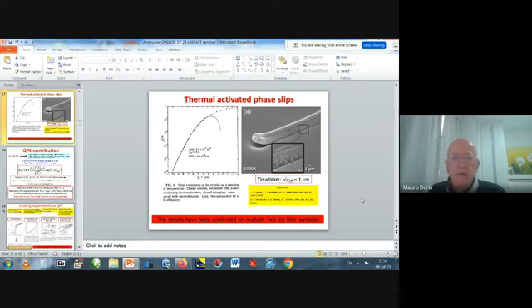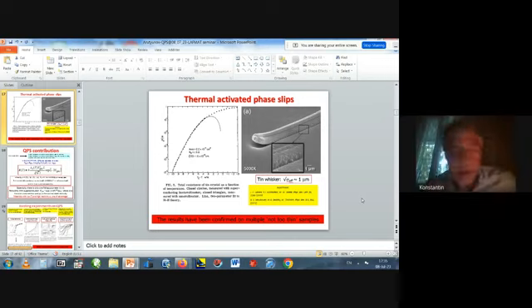And perhaps it would have interesting properties, I mean, associated to this large mean free path. You're absolutely right. Bismuth is a very interesting metal because it has anomalously low Fermi energy, 28 milli-electron volts, and in some particular directions, it has very small effective masses, 10 to minus 3 of free electron mass. So quantum phenomena in bismuth might be obtained at sufficiently large scales.